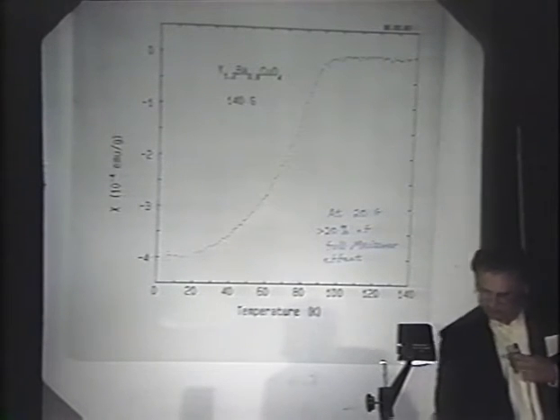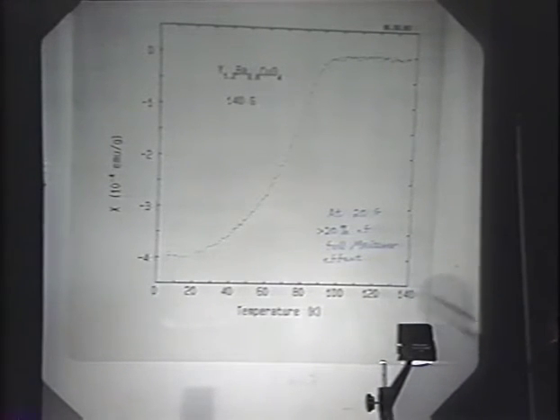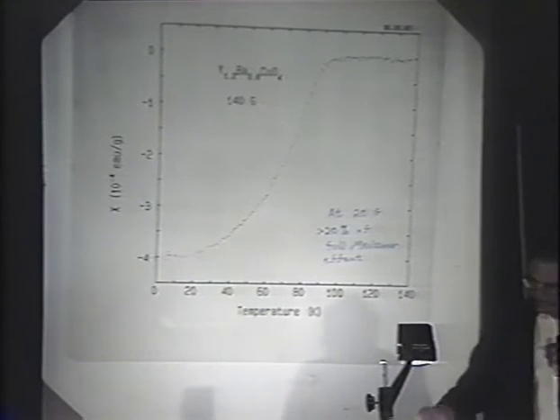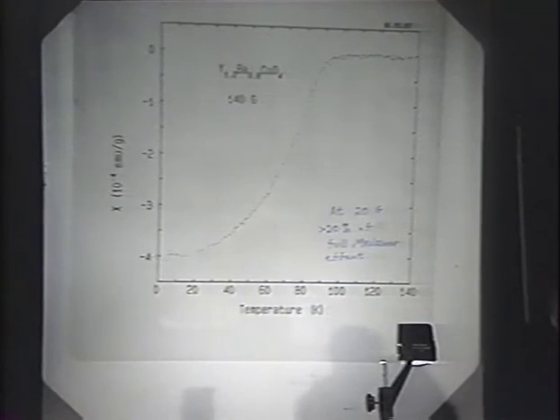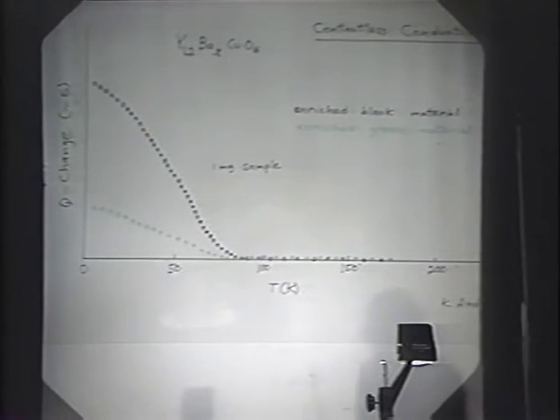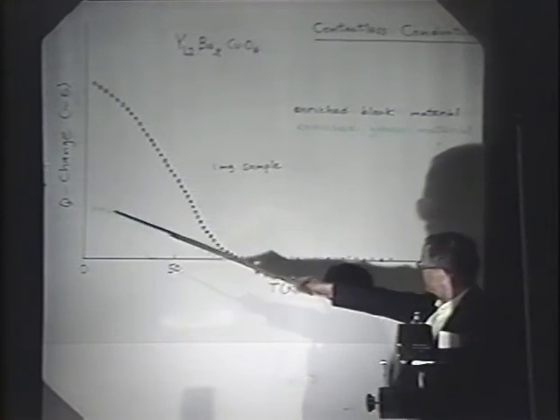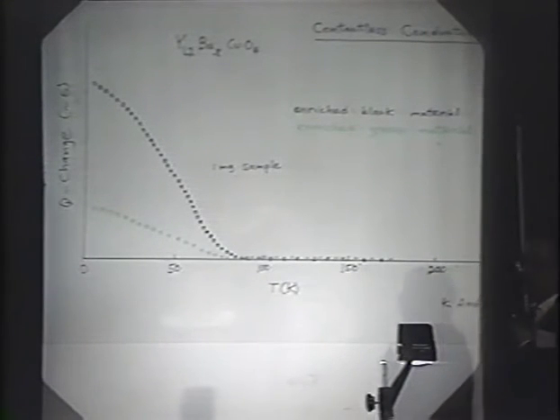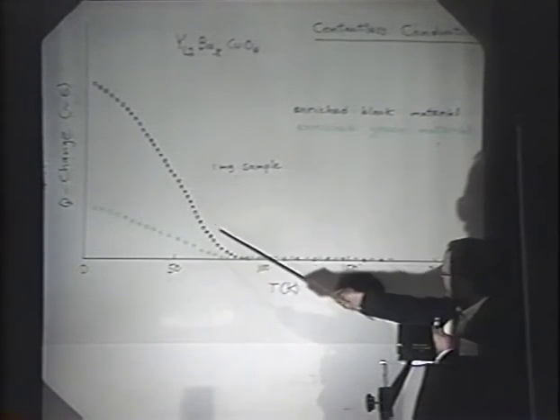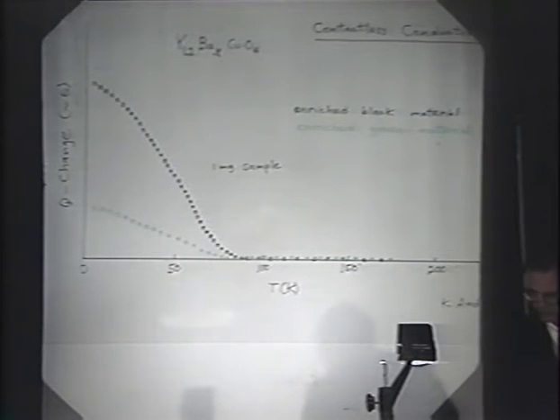We've also made the yttrium barium compound, which has a Meissner effect setting in at about 85 to 90 degrees. We get about 20% of a full Meissner effect at 20 Gauss. This is measured at 140 Gauss. This sample was loosely packed, so we could actually pick out, this is Paul Chu's composition, and Klaus Andres was able to, in an afternoon, pick out the black pellets from the green material, and using his marvelous contactless resistivity apparatus, where you can measure the resistivity on a milligram sample, he was able to show that the green sample, that's the green dots, which still had a bit of the black material in it, had far less conductivity than the black material. So he proved that the green material is not superconducting, the black material is.